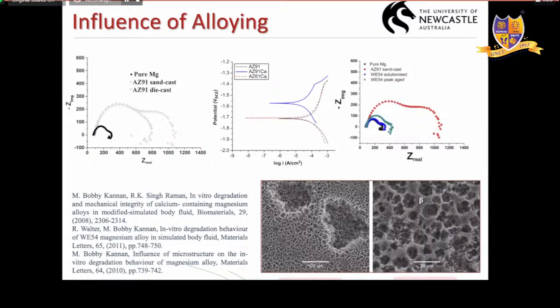And more importantly, I'll touch upon two things. One is this. Look at this. This is a sand cast alloy. This is an SEM picture after the degradation testing, and you see these large pits there. These pits mean the degradation is not uniform. It's non-uniform, localized. We don't want this kind of degradation because these pits can cause local failure. This can act as a stress riser when there is loading, and it can fail catastrophically without any warning, which is quite dangerous.